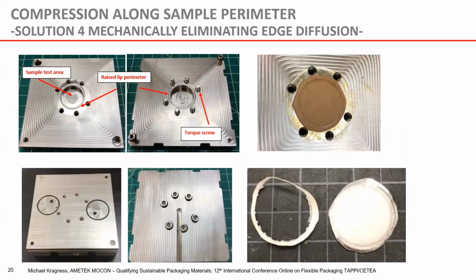And these are some real pictures of the actual test cell. You see we have the raised lip perimeter, and then we have our screws. We would torque those screws to some specification, and that would cause enough force to compress the material so there's no edge diffusion. And if you look at the picture on the top right, that's what a sample looks like after it's been compressed. You can see a very clear area where the compression took place.